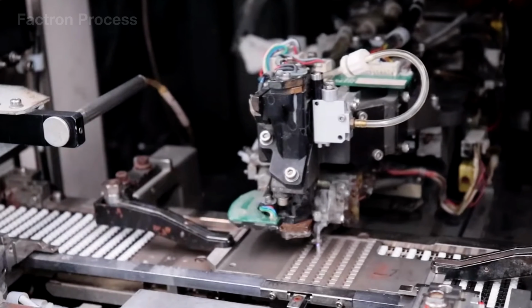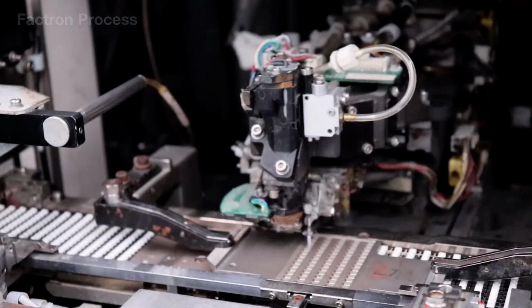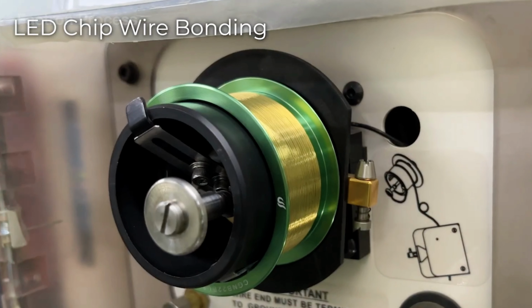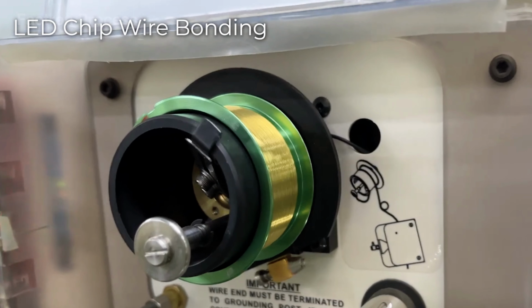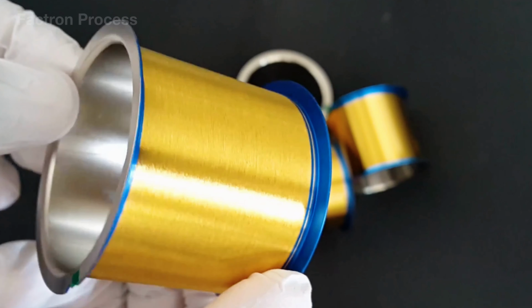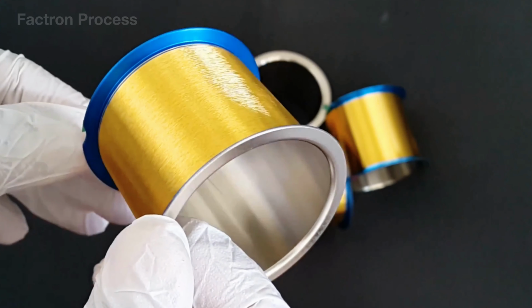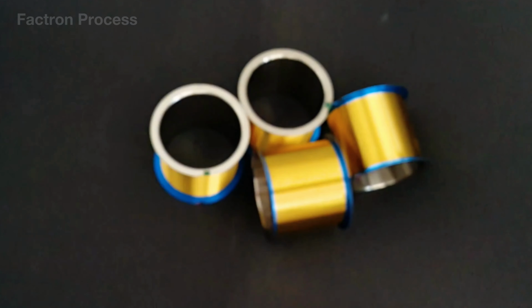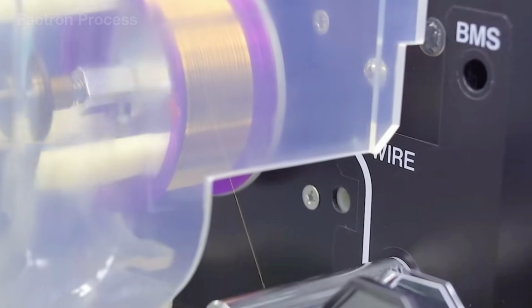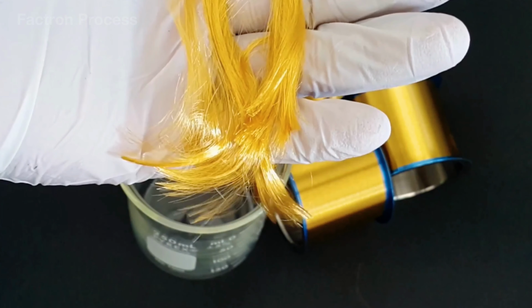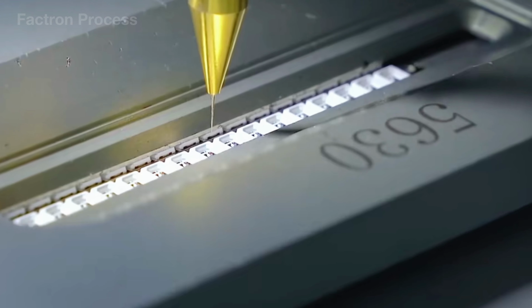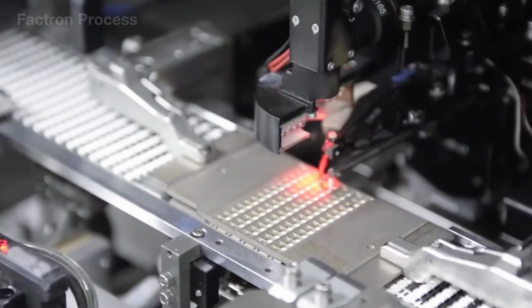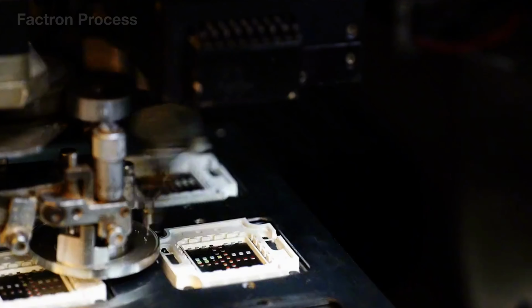Once the chip has been secured to the package, it still cannot receive electrical current. At this stage, a wire bonding machine uses an ultra-fine gold wire to connect the electrodes on the chip to the two metal terminals of the LED package. The gold wire has a purity of approximately 99.99% and a diameter of only 18 to 25 micrometers, making it several times thinner than a human hair.